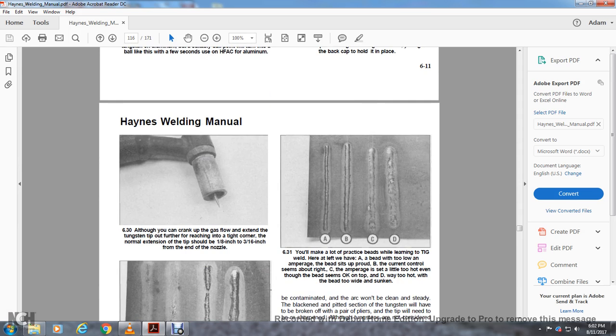Alright, 630. Although you can crank up the gas flow, the tungsten tip should stick out the normal extent from the cup, which is 1/8 of an inch, 3/16 of an inch for the tip.